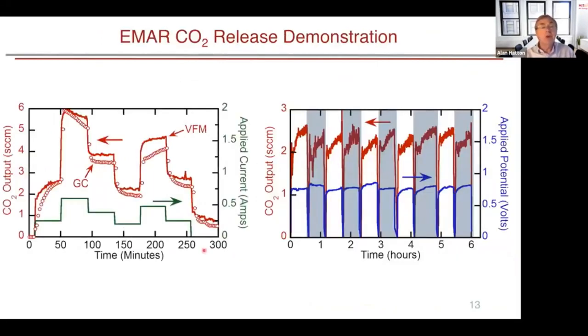Just to show you how this works, this is the applied current that we apply across that cell, and the higher the current, the greater the rate at which we release copper ions in solution, and therefore the greater the rate at which we will release CO2. And indeed, as we change the current passing through the system, we change the amount of CO2 that's being released directly, as shown here. Typically, we can get on the order of 80 to 90% Faraday efficiency for these systems.